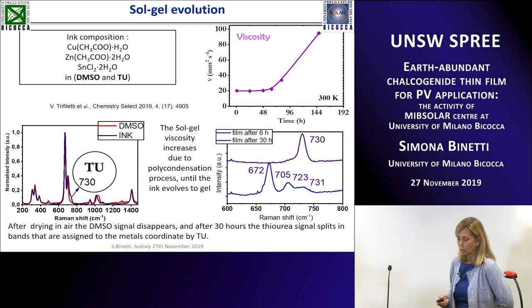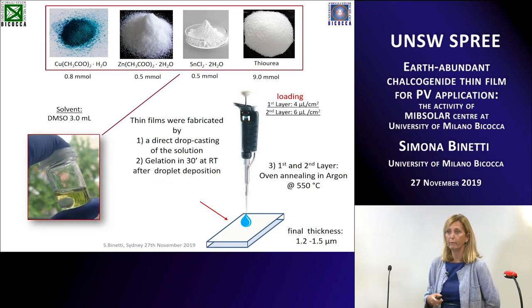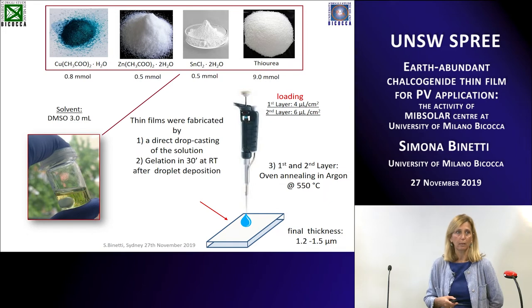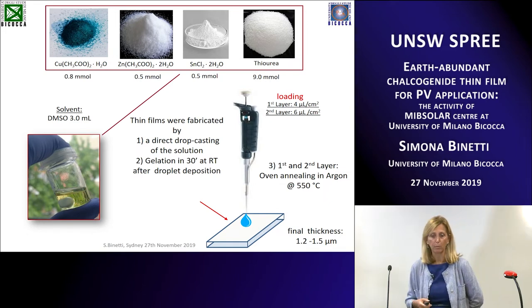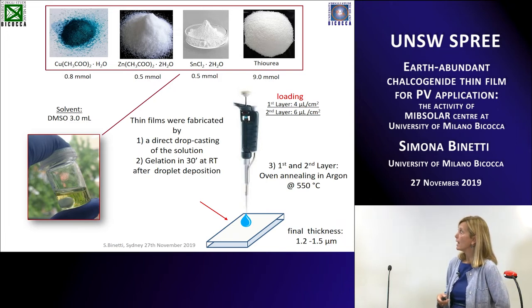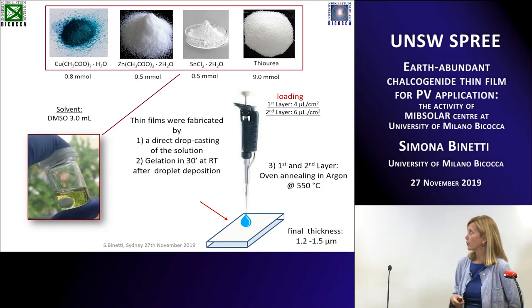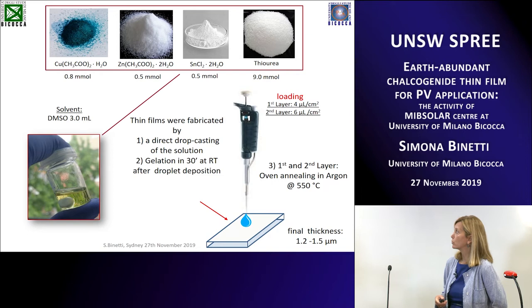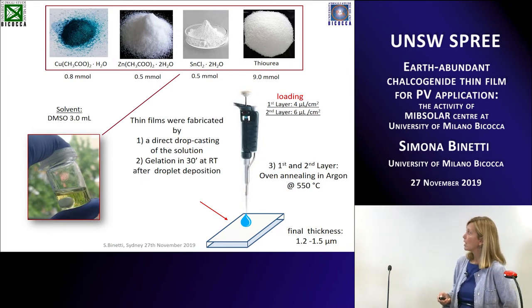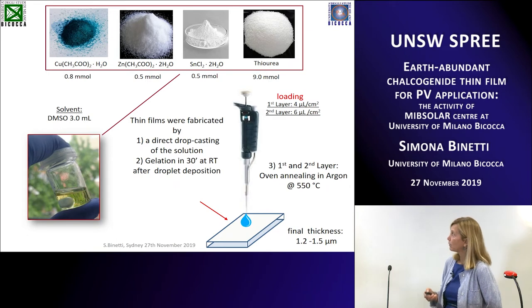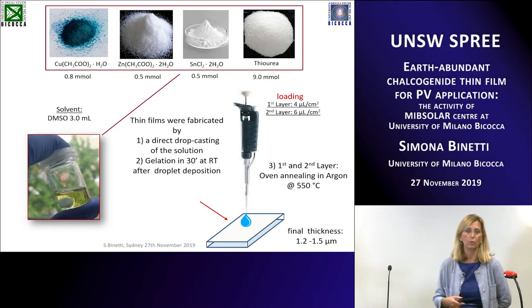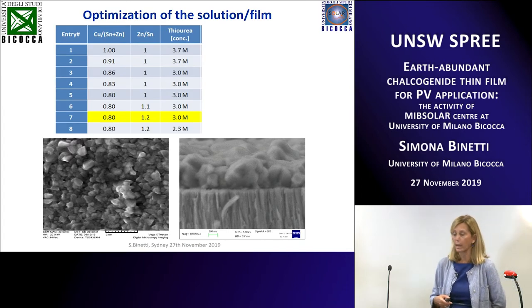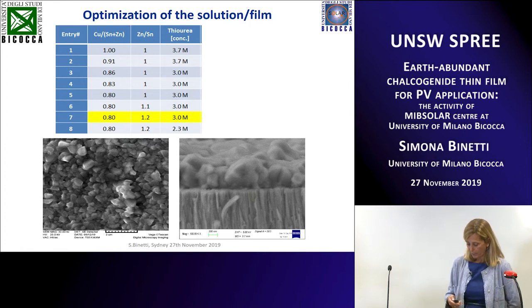Because then, after the optimization of the molecular ink, we just prepared our film in a very simple way by a direct drop casting method on the substrate, of course, a substrate coated by molybdenum, for instance, or FTO glass substrate. And then, after a two-step process, annealing in argon, just in argon, without sulfur, at 550 degrees C to get a final thickness of around 1.2-1.5 micrometers. So it's really a very simple method. We optimized, of course, the solution composition, the ratio between the components in this solution, in order to get the best composition in the film in terms of copper-poor and zinc-rich ratio. And we have grains in the order of 200-300 nanometers.